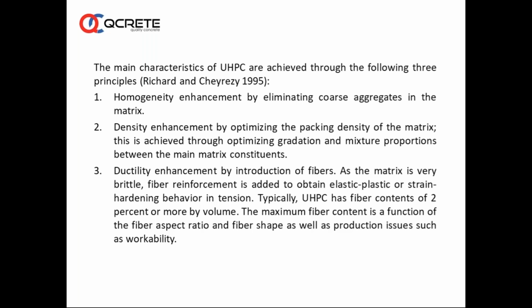So the most important characteristic of ultra high performance concrete is its homogeneity, and this homogeneity is enhanced by eliminating coarse aggregates. If you have a lot of coarse aggregates of different sizes, like in the case of normal concrete, the homogeneity may be lost. That is the reason the shift is towards finer particles, which can be packed well and which will give enhanced performance. Density enhancement is by optimization of the packing density of the matrix. This is achieved through optimizing gradation and mixture proportions between the main matrix constituents.